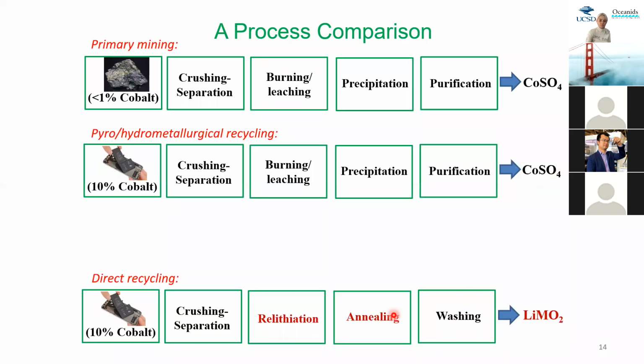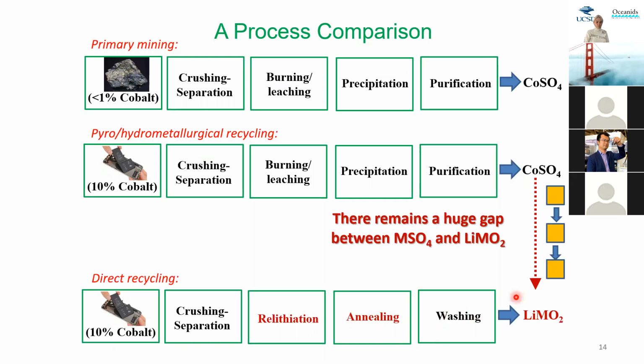So in terms of total number of boxes, it looks similar, but if you look into the details, there remains a huge gap from this metal precursor to the cathode materials or lithium battery materials, because we have to take this precursor through dissolution, precipitation, mixing, and sintering until we can obtain these lithium battery cathode materials. So hopefully I used these slides to distinguish the traditional mining process, the current industry pyro and hydrometallurgical processes for recycling, and then to highlight the difference of direct recycling.